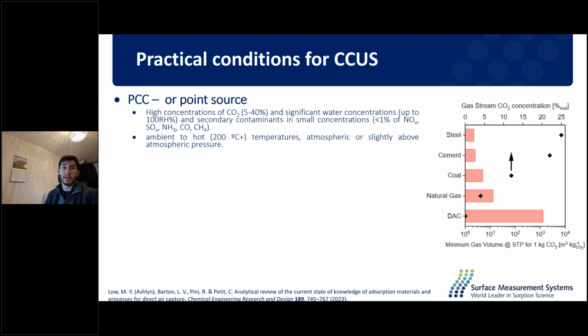These streams that are currently just flushed to the atmosphere have relatively high concentrations of CO2, so 5 to 40% by volume. This is why they're prime targets for CO2 capture, but also significant water concentrations and secondary contaminants, often in relatively small concentrations, like NOx, SOx, ammonia, carbon monoxide, methane, essentially incomplete burning. They tend to be hot to ambient. As you imagine, a flue gas tends to be pretty high temperature, so much above 200 C, but often they're cooled down. And pressure-wise, it's atmospheric or slightly above atmospheric.